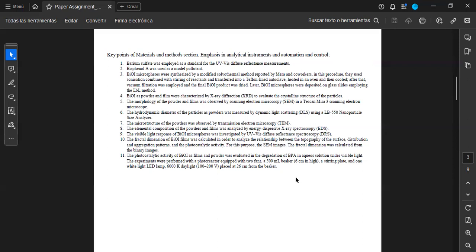This is abbreviated as TEM. After that, the elemental composition of the powders and films was analyzed by energy dispersive X-ray spectroscopy. This is abbreviated as EDS. Then, another study was done. So, the visible light response of BiOI microspheres was investigated by UV-Vis, in the mode of diffuse reflectance spectroscopy. This is abbreviated as DRS.